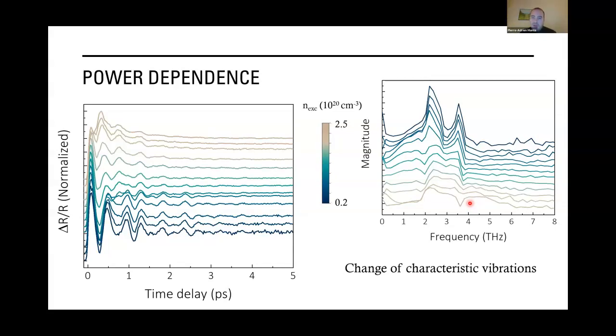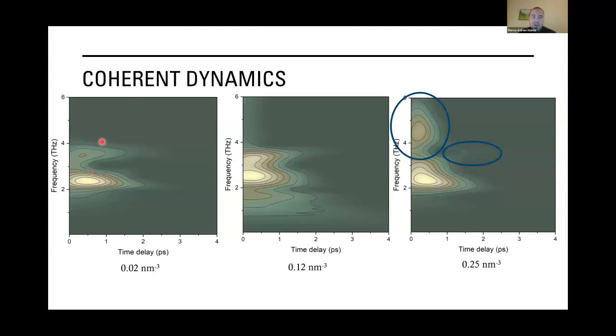So what we performed to understand this better is a time frequency analysis of this signal. At low power, we see what I presented previously: these two dominant amplitude modes, and we can also observe, at 3.1 and 1.9, the zone-folded phonons. But when we increase the power, we start to see the appearance of a phonon mode at higher frequency, and we can see that the 3.6 terahertz mode seems to disappear and reappear at a later time scale. This is even more observable at higher power, where there's almost no contribution of the 3.6 terahertz until 1 picosecond, and the signal at early time scale is dominated by a vibration at 4.5 terahertz.